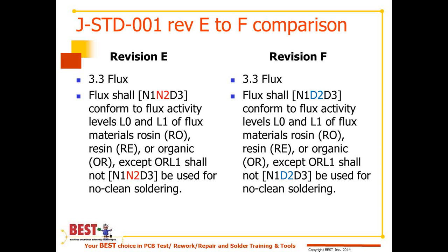Under 3.3, they changed the flux. Now it's a defect for Class 2 if it doesn't conform to the flux activity levels of L0 and L1 for fluxes. And it also says it's a defect for OR L1 fluxes to be used in a no-clean soldering environment.